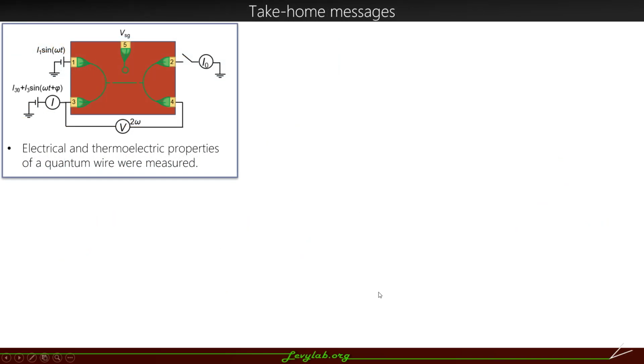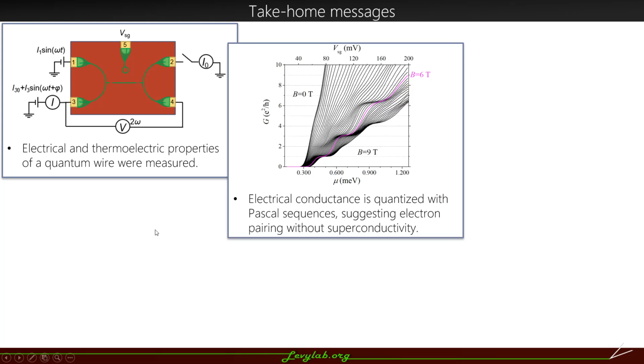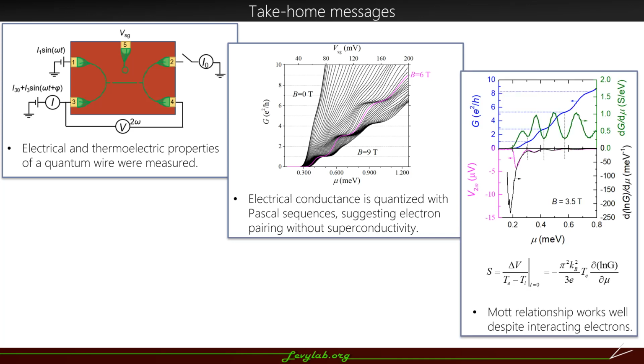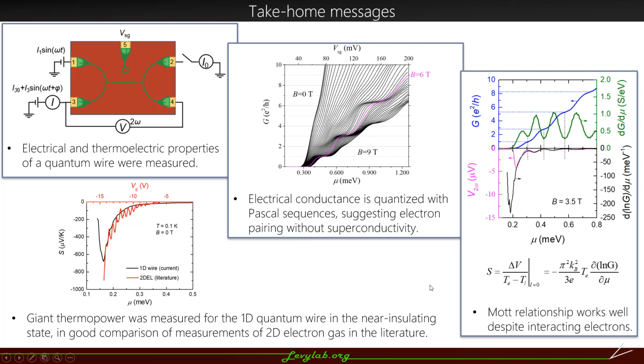So to sum up, we have measured the electrical and thermoelectric properties of a 1D quantum wire. The electrical conductance is quantized with a Pascal sequence, suggesting that we have electron pairs outside the superconducting regime. And we have measured the thermopower. We found that the thermal voltage compares very well with d log G / d mu, and the Mott relationship works quite well despite the interacting electrons in a quantum wire. And we have derived the Seebeck coefficient, which compares well with the literature measurements, which shows a very high Seebeck coefficient, especially in the near insulating state for a quantum wire.